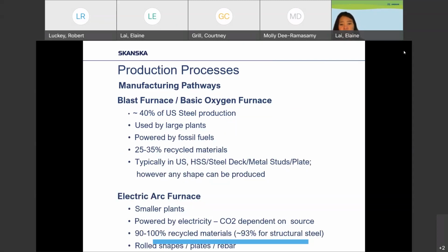So as outlined here, about 40% of US steel production we use the basic oxygen furnace, or BOF for short. These are typically larger plants, typically also powered by fossil fuels. For those that are using recycled materials, you can see that it can incorporate about 25 to 35% recycled steel as part of that process. The typical shapes that can be produced in the BOF are HSS, deck materials, studs, and plate. However, any shape can be produced in the basic oxygen furnace.